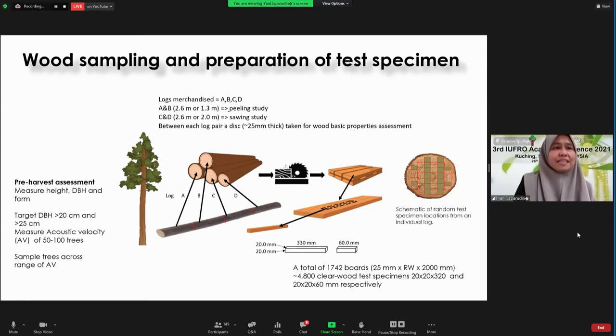But for this particular wood quality evaluation and the assessment of mechanical performance, the samples were prepared along with the sawing study. From the sawing, a total of 1,742 boards were prepared with the dimensions there. And we have 4,800 clear wood test specimens with the respective dimensions here for the mechanical testing. And you can see the diagram here shows the schematic random test specimen location from an individual log to allow us to understand the radial variation of the mechanical properties.